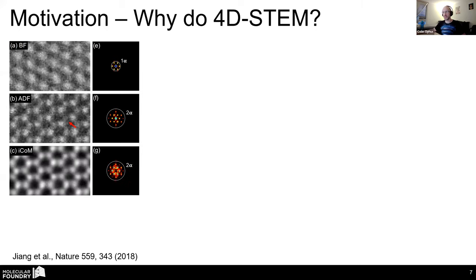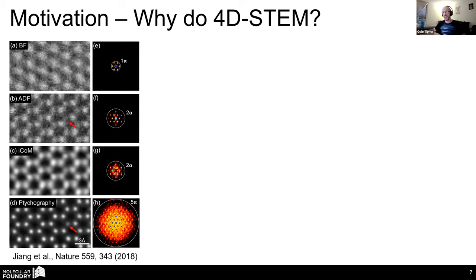If you switch to phase contrast imaging, in this case, something called center of mass differential phase contrast imaging, this is akin to what the biologists use. It's much better for weakly scattering materials. But it doesn't really push the resolution of the technique. It boosts the signal to noise because it's much more dose efficient, but you can see the maximum Fourier components there are about the same as the incoherent methods. But if you instead use the image of the probe to fully deconvolve all of the aberrations in your probe from your sample, you can see both a dramatic increase in signal to noise and in resolution. And so this is from the Cornell group's Nature paper here showing sub 0.5 angstrom resolution of molybdenum disulfide.